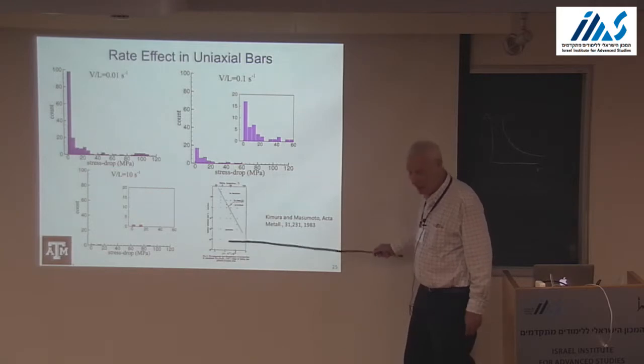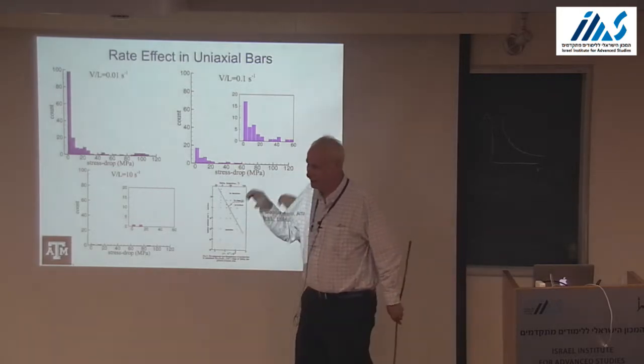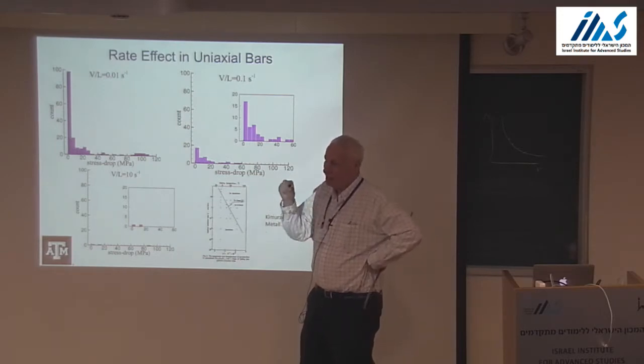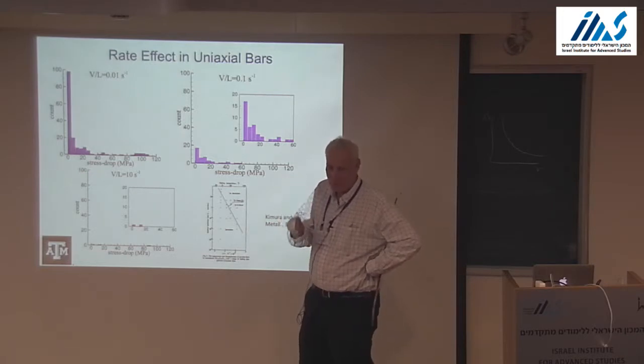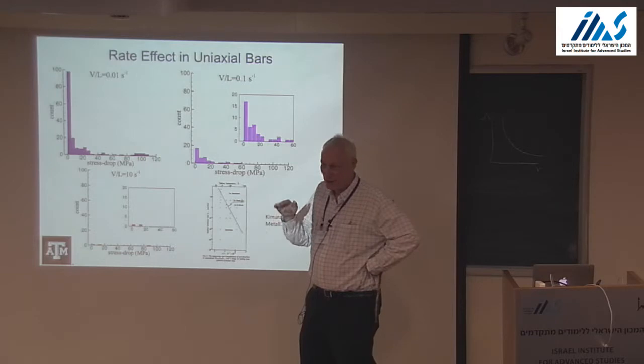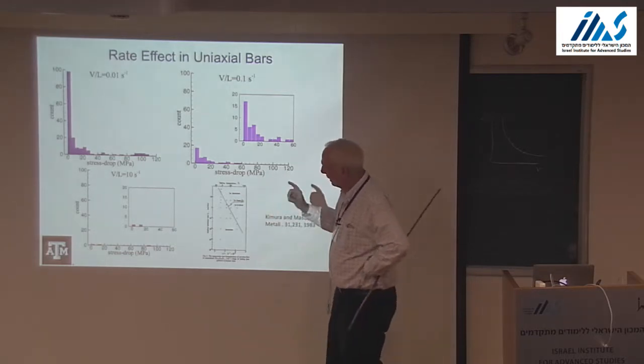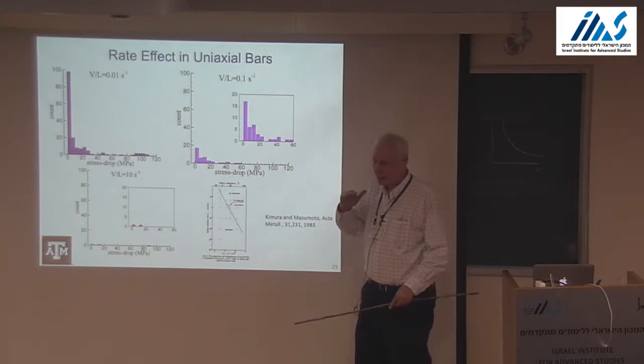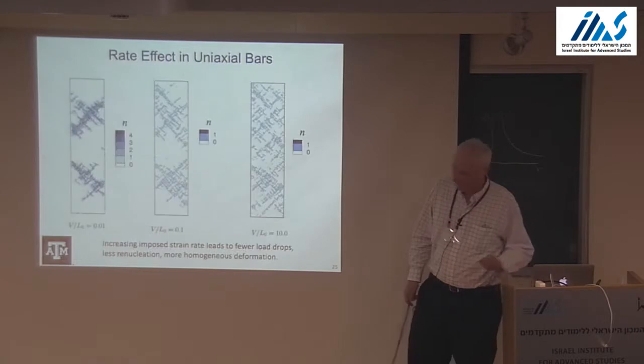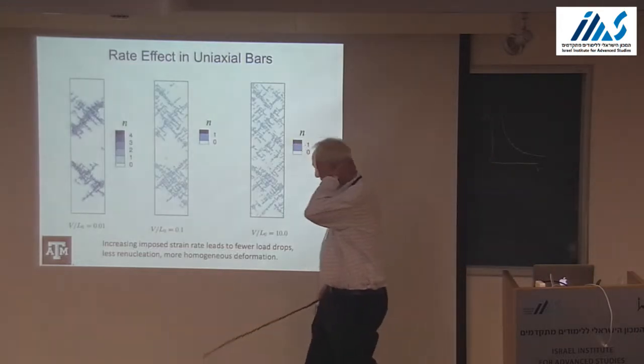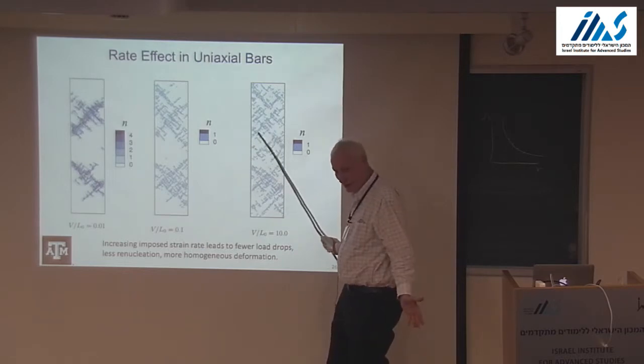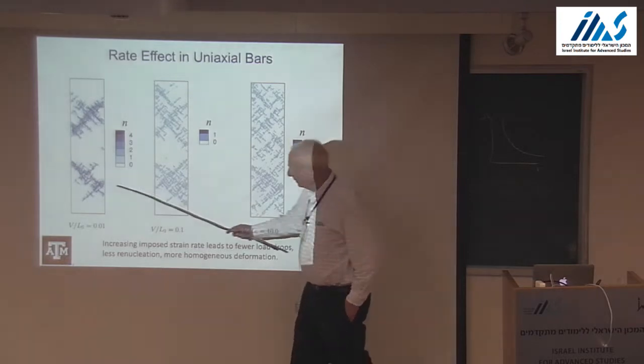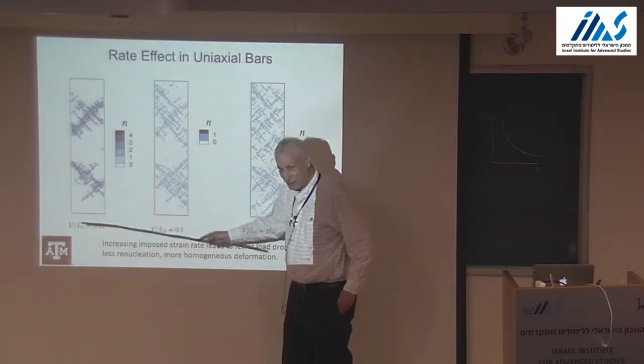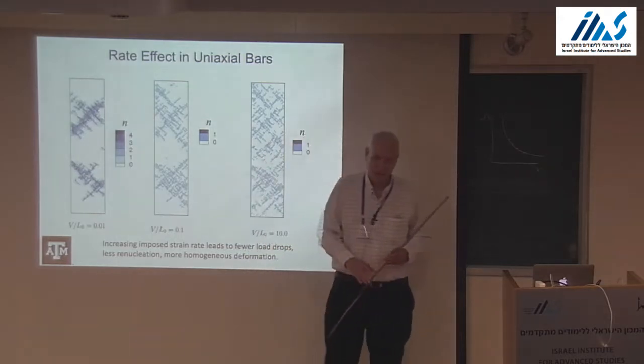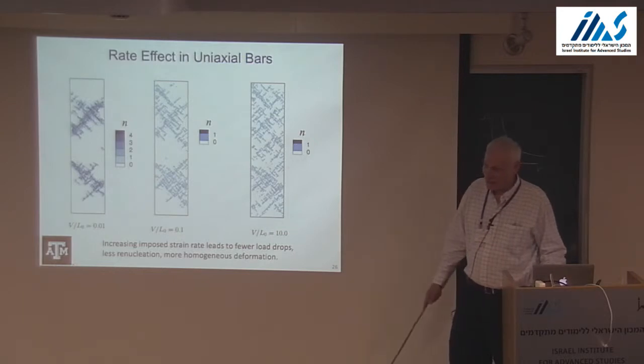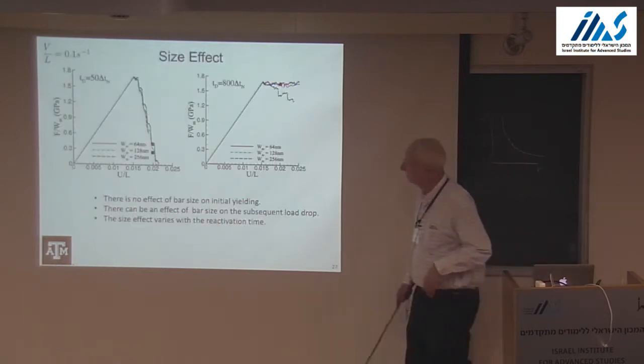And again, at high rates, of course what we do is not at all physically accurate, but what it does say is the time scale is very important here, and perhaps the statistics of these drops and these avalanche effects give a lot of insight into the time scale of the governing process. What also happens with rate: at 10 per second you get a much more homogeneous type of deformation. At slower rates, these large avalanches occur in shear bands that just form naturally. So there's a strong rate effect in these materials on the shear band evolution.